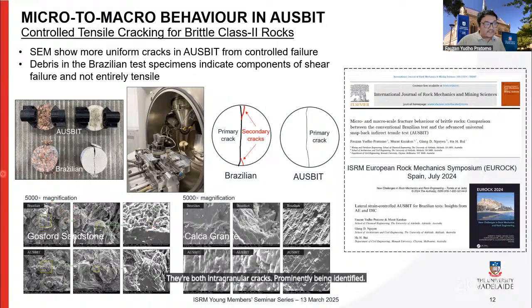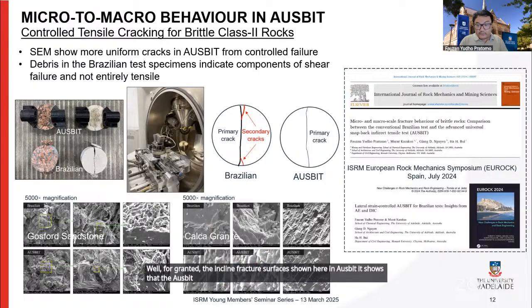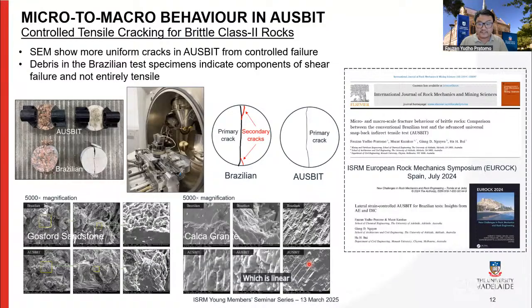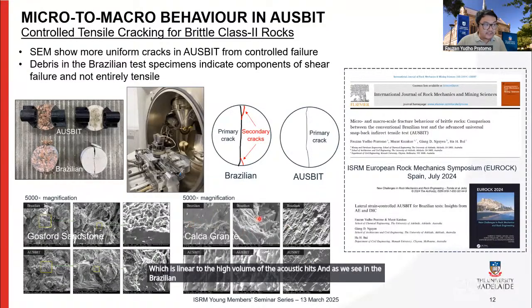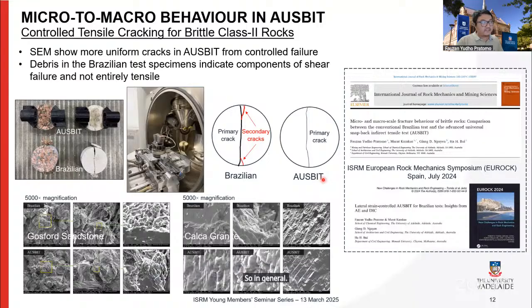While for granite, the inclined fracture surfaces shown here in AUSBIT show that the AUSBIT specimen produced more uniform, intense fracturing, with smaller widths between microcracks, which is linear to the high volume of the acoustic hits. And as we see in the Brazilian test, we have quite some amount of debris. That indicates components of shear failure and not purely failing in tension. So in general, there is a strong link between the DIC, the acoustics, and the SEM.